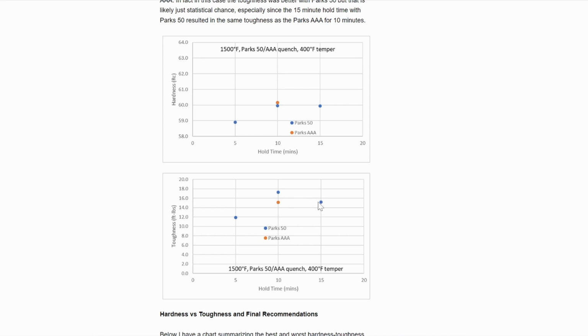You can see the toughness didn't really change between 10 and 15 minutes. So knife makers are very worried about grain growth often. They want to have a very short hold time to avoid grain growth. But as I mentioned, temperature matters more than time, and under austenitizing is also detrimental. You can see we had both lower hardness and lower toughness.